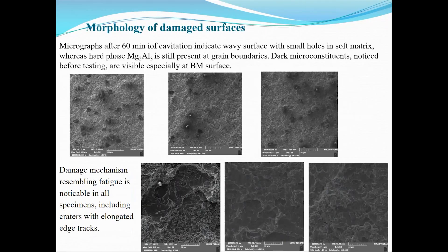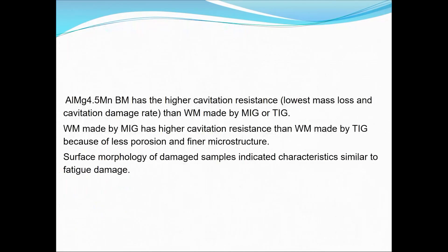Probably for the TIG process we can use better technology in the future, if it is of interest to this investigation. Here are those fractographs — those damaged surfaces — and you can see that the damage mechanism actually resembles fatigue. It was noticeable in all specimens, and that is quite an interesting observation: this ultrasonic testing mechanism is close to the fatigue mechanism.